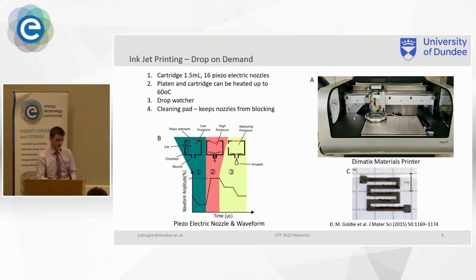And we can change that speed by changing the voltage that is applied to each nozzle. And on the bottom left there is an illustration of how we can create these droplets using a waveform which is applied to the piezoelectric nozzles. And this waveform can be broken down into 3 sections. The first, which is complete relaxation, no voltage is applied to the nozzle, which creates a low pressure, pulls the ink into the nozzle. We ramp the voltage up to 100%, which we set dependent on the velocity that we want. That pushes the ink out, and we gradually reduce the voltage to break the droplet into a teardrop, and then reduce it further to snap it off so we get a single droplet.